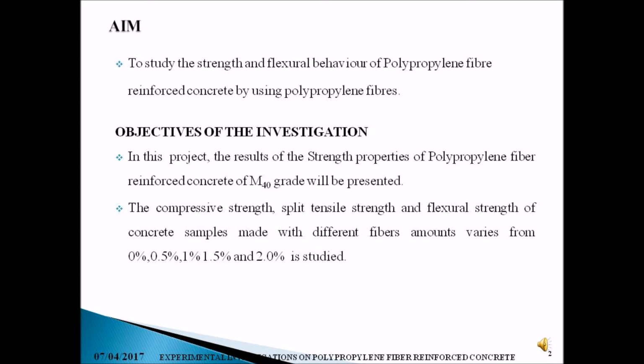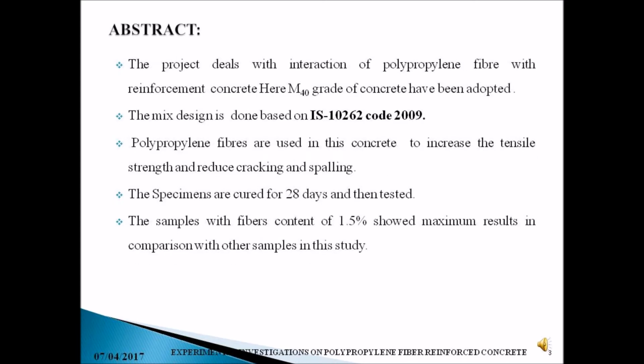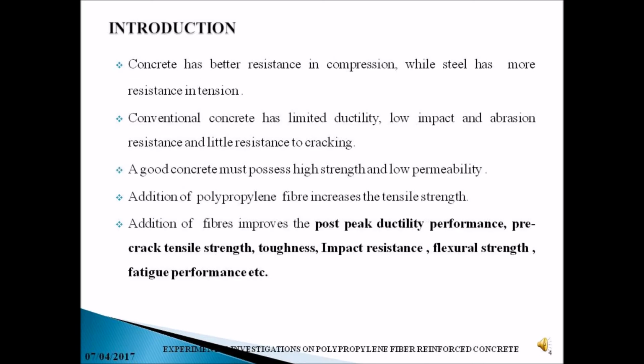by using polypropylene fiber. Here polypropylene fibers are added in different ratios such as 0.5, 1, 1.5 and 2%, and various tests have been conducted. Here M40 grade of concrete is being adopted. The mix design is done based on code book IS 10262-2009. Specimens are first cast and cured for 28 days, and then tested, and we came to a conclusion that 1.5% fiber showed maximum results.